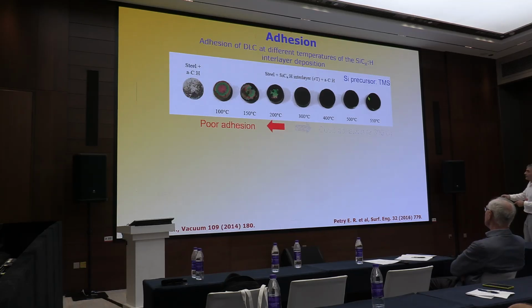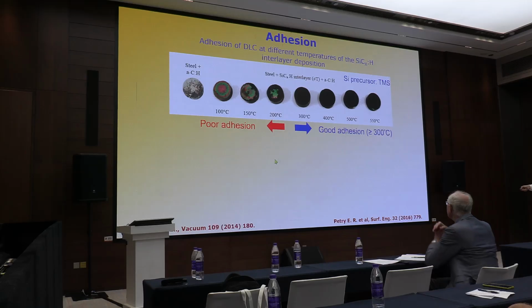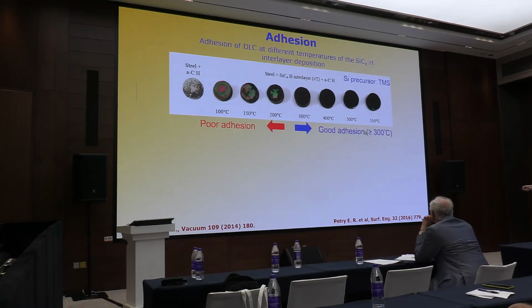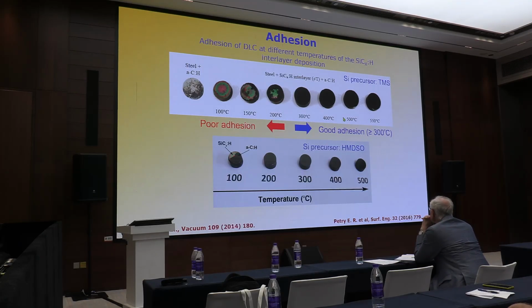Here we have poor adhesion, and here we have good adhesion. These samples were made using a silicon precursor, tetramethylsilane, to deposit the interlayer between the steel and the amorphous hydrogenated carbon. And here we use hexamethyldisiloxane. This is another silicon precursor to deposit this interlayer. And the behavior is the same.